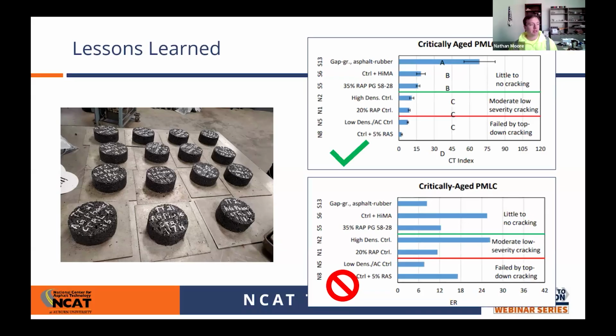lineup with performance. So I'm showing you two pictures here. Again, Randy will probably dive more into these, but this is the same exact mixes with two different tests. The one on the top, above that green line, was little to no cracking, and below the red line was sections that failed. And so for the critically aged IDEAL-CT, the lab test lined up with the field tests. Whereas you go to the energy ratio test, which is another test that we ran back in 2015, the numbers were kind of all over the place, and the lab data did not line up with field performance.